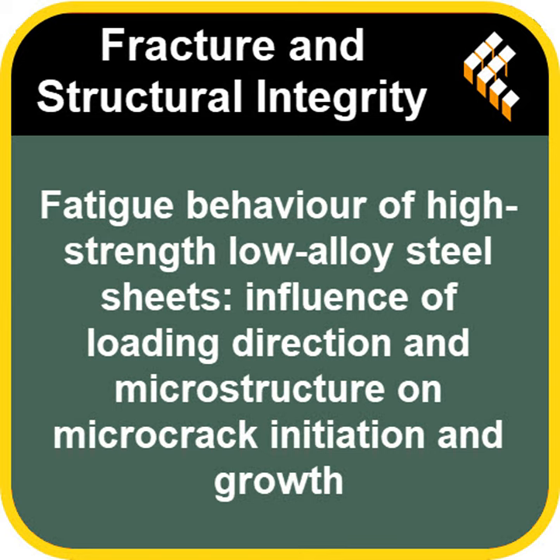That's right. For RD, the plot relating strain to fatigue life was pretty much linear, which is often expected. But for TD and DD, it showed this clear bilinear trend, like the line bent at a certain point. A kink in the curve. Exactly. And importantly, this wasn't because of different phases acting up, which you sometimes see in other types of steel. This suggested a more fundamental shift in how the material was failing.